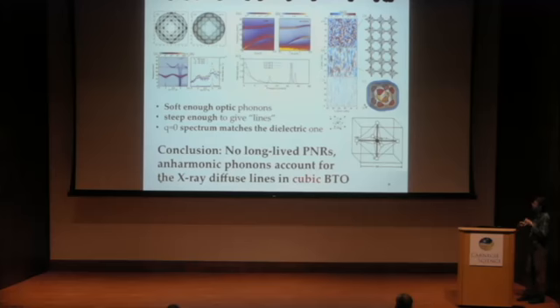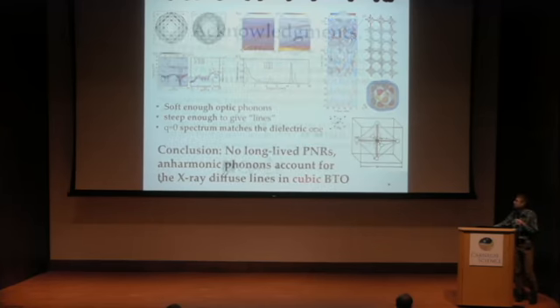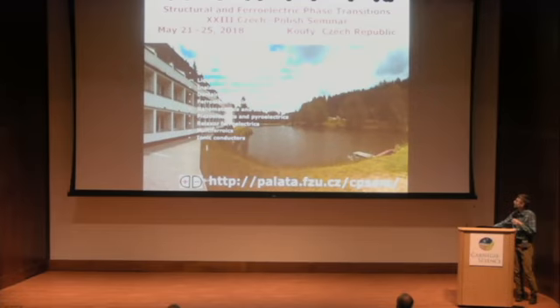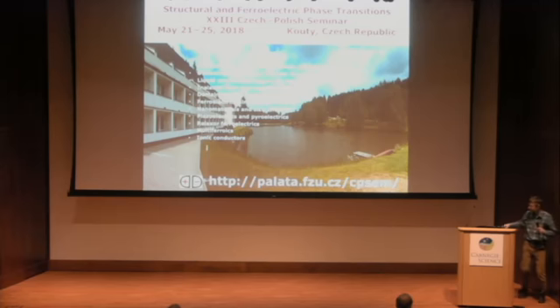So the conclusion is that they are soft enough optic phonons, steep enough to give lines, the q=0 spectrum matches the dielectric one, and the conclusion is there are no long-lived PNRs in cubic barium titanate. I mean the one which is the homogeneous bulk without defects. And so basically it is a displacive material with a displacive cubic phase. That's my conclusion, acknowledgements, and a brief advertisement. Thank you for your attention.